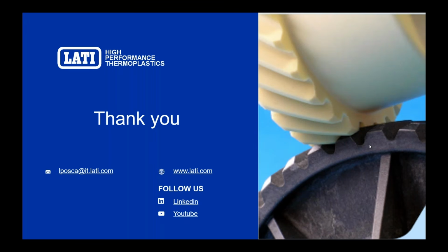I have a question I can read. Can the same additives be used for other resins? The answer is yes, but also no, because as you know, ultra-high molecular weight polyethylene is a low melting point resin, so it can be used, for example, for resins like polyamide 66, which shows a processing temperature around 270, 280. But for high thermal polymers like PPS and PEEK, it's a little bit more complicated to maintain the thermal stability of this kind of filler, so it depends.